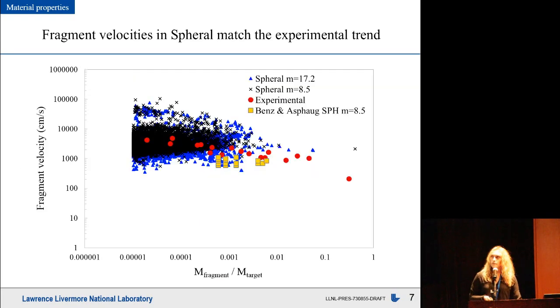We compared the fragment velocities in spheral using M equals 17.2 and 8.5 to the experimental results and to the results by Benz and Asphaug for parameter M equals 8.5.